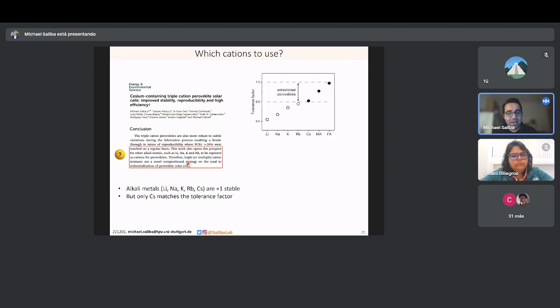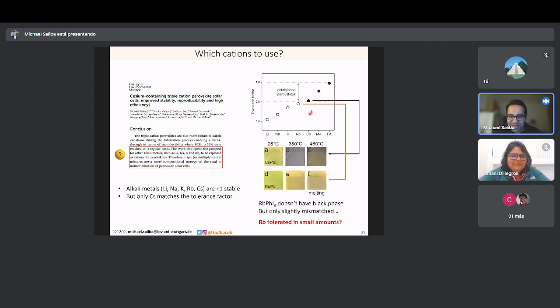And so then the next logical situation would be, of course, to go down in the periodic system. You could say, okay, there is francium. That's true. Francium is also larger than cesium, but it's radioactive. So that wasn't really an option. Although if you were to take francium, radioactive atom, nobody would talk about the lead toxicity anymore. So that could be a kind of advantage. And you see here, as predicted, only the cesium has a black phase, albeit at high temperature, and the rubidium never has a black phase at all, no matter at which temperature.